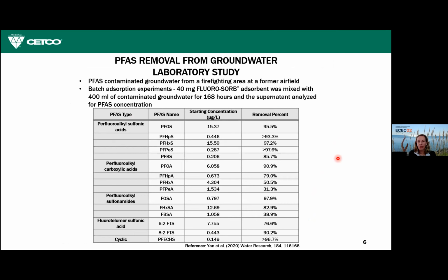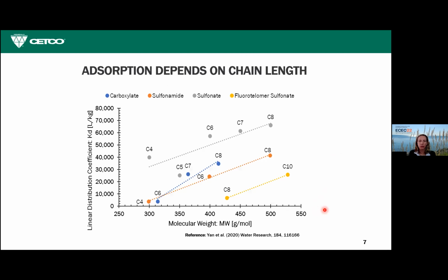This is some basic lab studies done at McGill University. These are batch studies with contaminated groundwater from an AFFF training area mixed with Fluorosorb and incubated. This is at equilibrium, and it's showing that Fluorosorb will adsorb the long chain PFAS very well. It still does adsorb short chain PFAS like PFPeA, but the percentage is reduced, and same with FBSA, another 4 carbon shorter chain PFAS. And that was also shown in the same study.